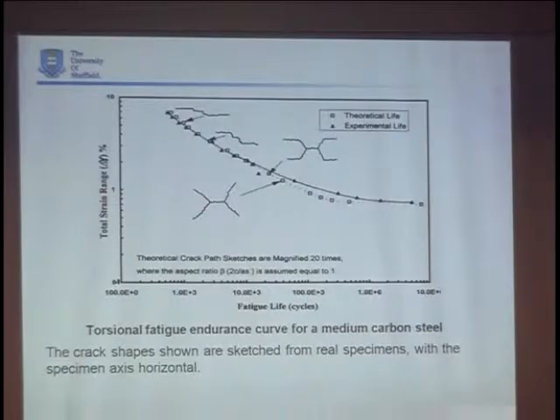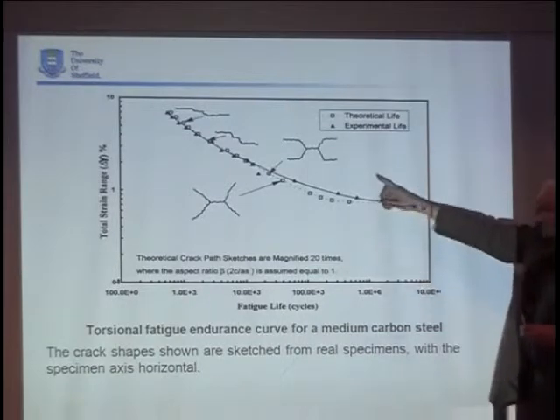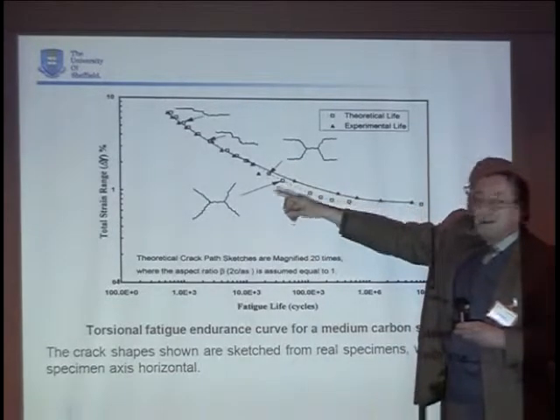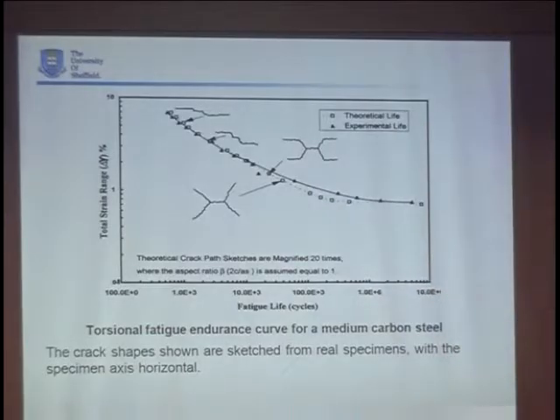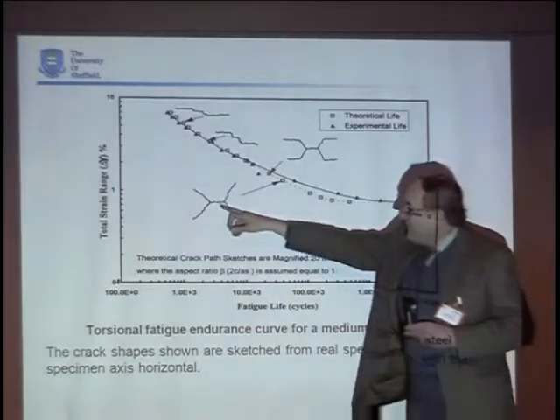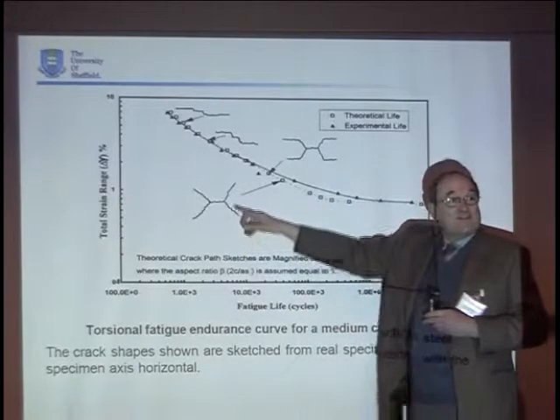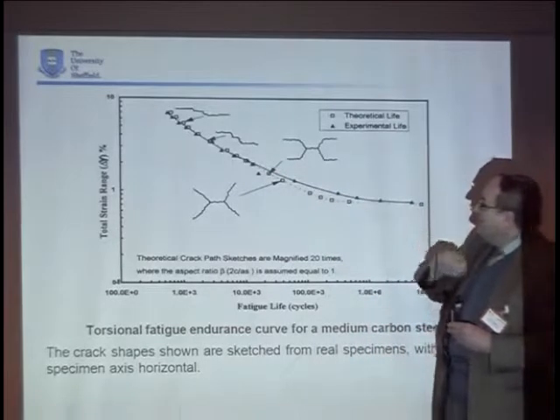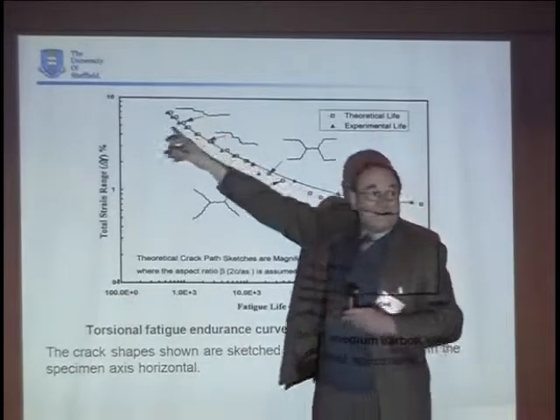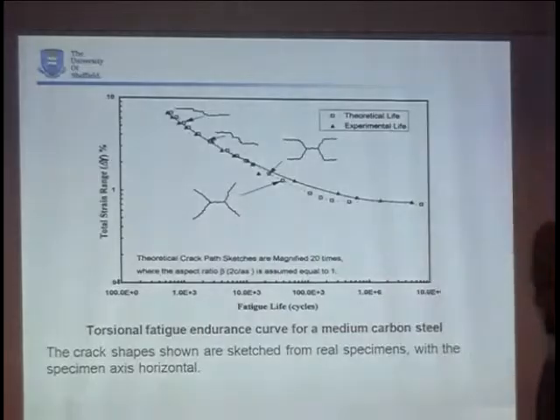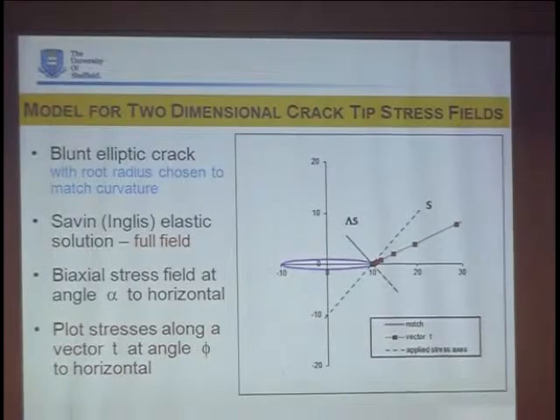Another example that you'll be much more familiar with probably is just torsional low cycle and high cycle fatigue. It's a fatigue curve. These cracks sketched are real ones taken off the samples that this research student was looking at. In high cycle fatigue, with a crack initiated in shear, it transfers into a Mode 1 like we had on the previous slide. In low cycle fatigue, you get much more shear mode cracking. So shear mode is quite possible to have in real life.